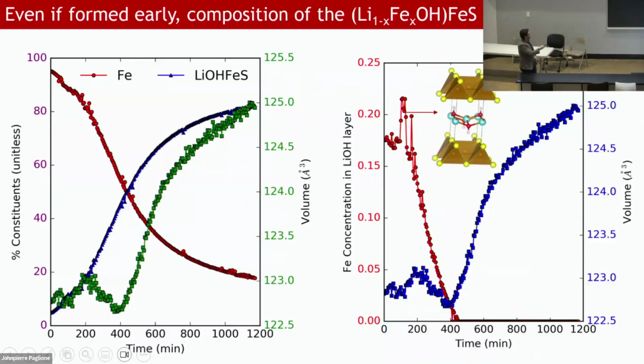And you can see that if you do Rietveld analysis of all those thousands of powder patterns, you can pull out the phase fractions. And one interesting thing about this is there's a little bit of iron that substitutes. It dopes, right? We have iron 2+, it dopes on lithium 1+, and it creates a cationic layer that charge dopes into iron selenide. Presumably that's why you raise the TC to 43 Kelvin. But what we see when we do the synchrotron is that the amount of iron that goes in there is pretty dynamic. It actually decreases and then it goes away.